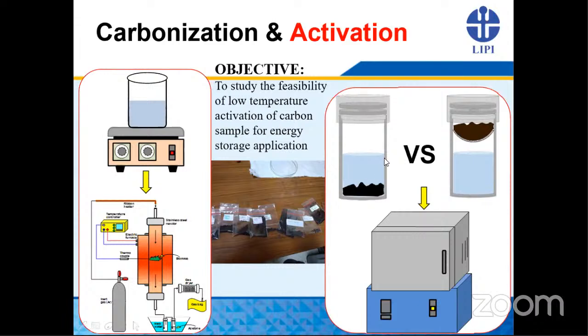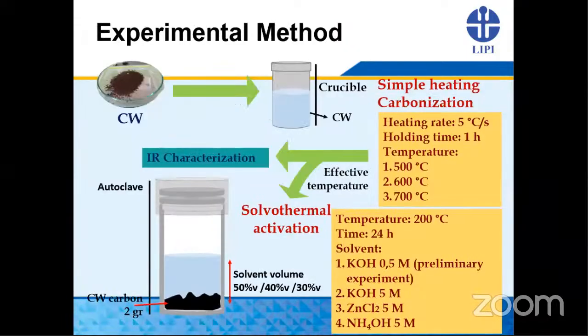So in here, the carbon sample will be boiled within the solvent, while in here the carbon sample will be steamed in the solvent vapor, and we put this one in the oven and heat treat it at 200 degrees C for 24 hours. So this is the experimental method.